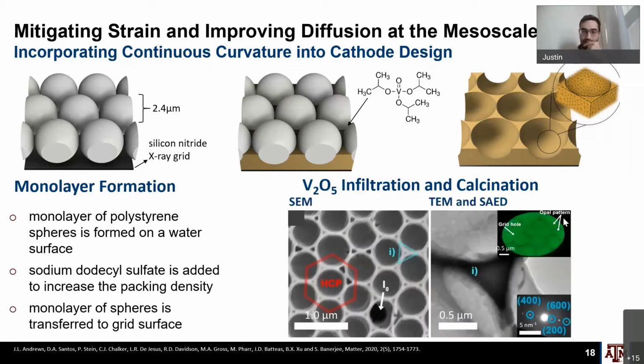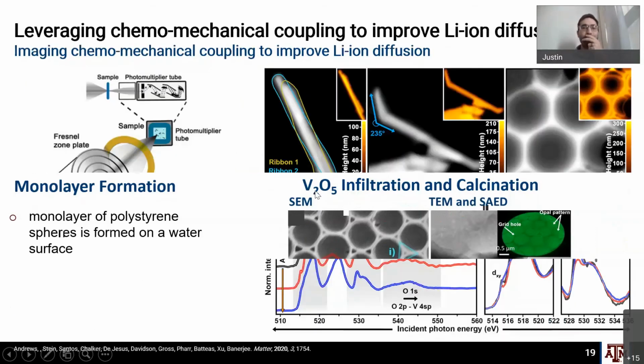This is some SEM and TEM of these materials. On a silicon nitride grid, we can grow these inverse opal patterns, and you can see they form nice nano bowls, if you will. Also, in some cases the films are fractured, and we can get I0 from these, so we can do our normalization and look at them in transmission mode.